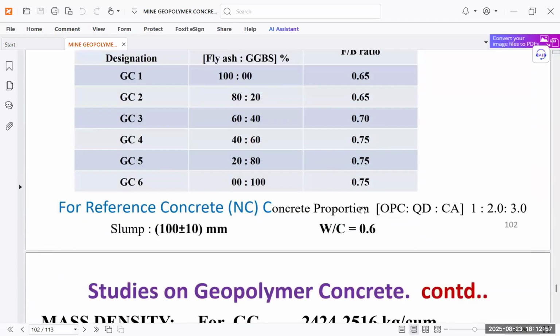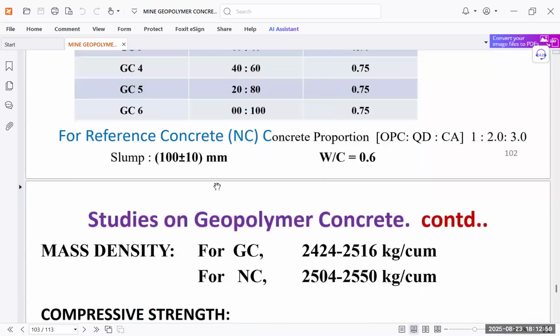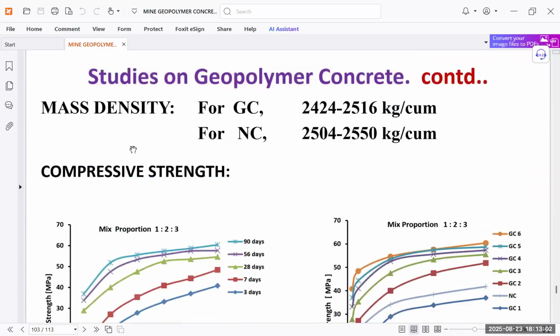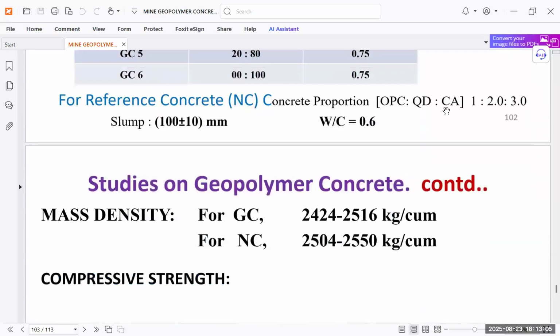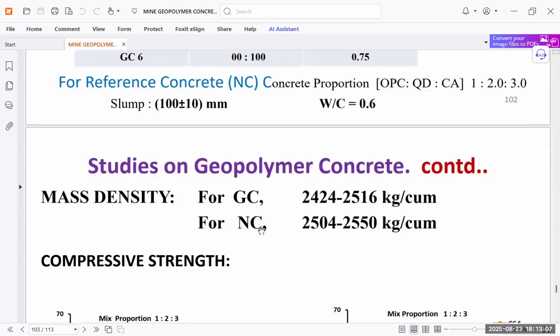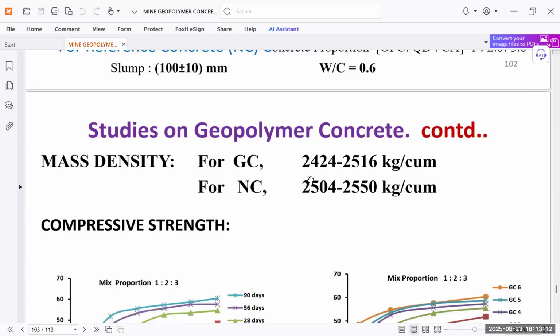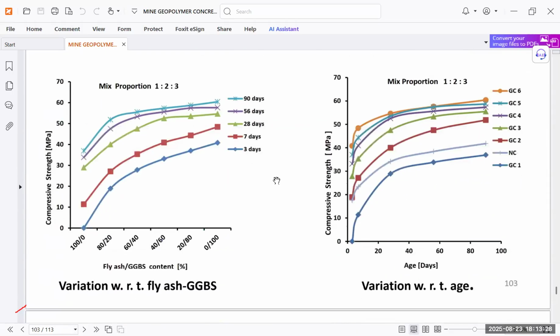For reference concrete, we have taken the concrete proportion something like this. So based on the studies on geopolymer concrete, we can compare it with NC. Here the reference concrete NC means normal concrete and GC is geopolymer concrete. The mass density for geopolymer concrete is 2424 to 2516 kg per cubic meter, and for normal concrete, as we already know, the mass density is 2504 to 2550 kg per cubic meter. The compressive strength we have compared for both.